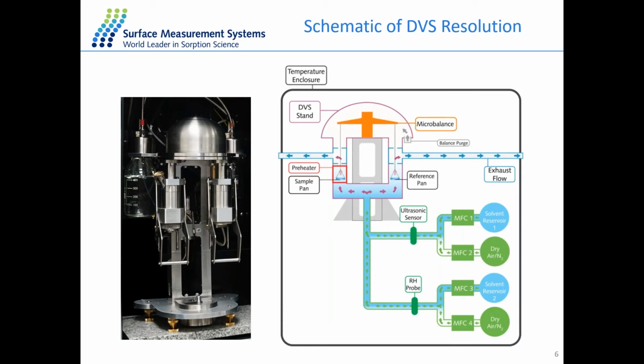As well as the competitive sorption of two different components. In the middle of the system here, we have our microbalance with a resolution of 0.1 microgram. It's connected to both the sample pan and the reference pan. And there are two bottles at the back of the system, one for water, the other for the organic vapors.